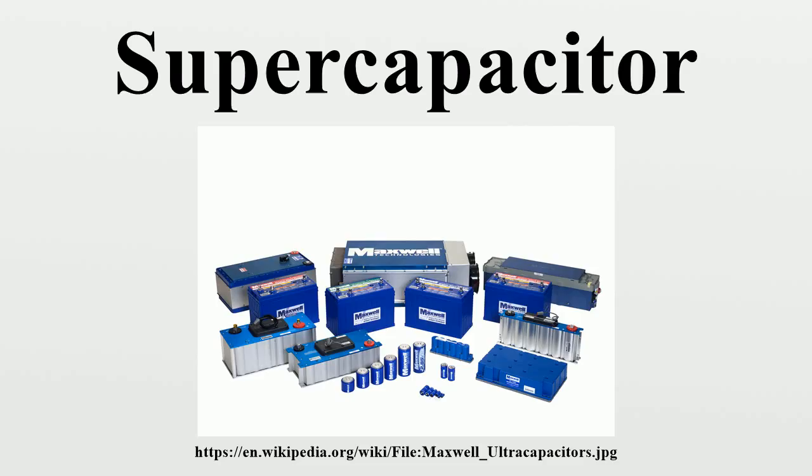Pseudocapacitance can originate when specifically adsorbed ions out of the electrolyte pervade the double layer. This pseudocapacitance stores electrical energy by means of reversible Faradaic redox reactions on the surface of suitable electrodes in an electrochemical capacitor with an electric double layer. Pseudocapacitance is accompanied with an electron charge transfer between electrolyte and electrode coming from a desolvated and adsorbed ion, whereby only one electron per charge unit is participating.